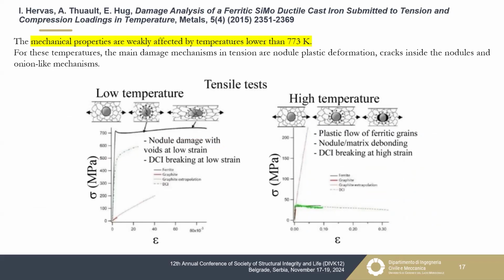This paper is instead focused on the role played by the testing temperature, and the authors found that below more or less 500 centigrade degrees, the main damaging mechanism was due to the nodule plastic deformation, followed by cracks inside the nodules and by a sort of onion-like mechanism inside these nodules. Instead, at high temperature, the ductile deformation of the matrix implied the debonding between the nodule and the matrix as the main damaging mechanism.